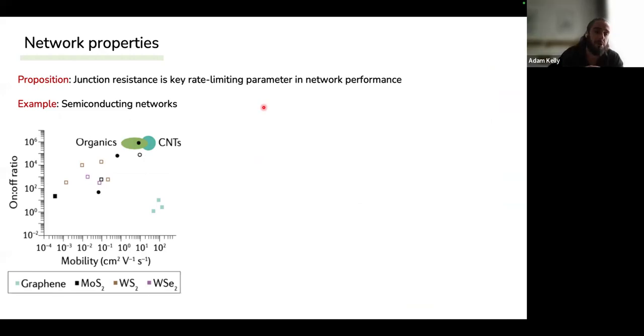So the example I'm going to show you here is semiconducting networks, where the way these are typically characterized for transistors is the on-off ratio versus the mobility. Where we have a material like graphene down here, which obviously has the high mobility of the zero bandgap semiconductor, but for the same reason, it has very low on-off ratios. And spread across the rest of the graph here, we have the TMDs, the transition metal dichalcogenides. Now, what we've noticed is that in the last couple of years, MoS2 has started to show mobility values that are competitive with organic materials and carbon nanotubes.